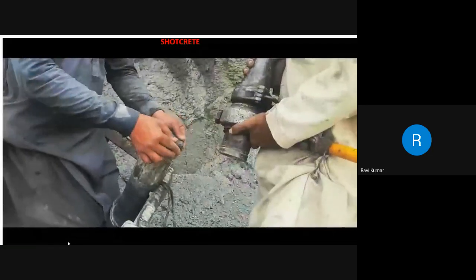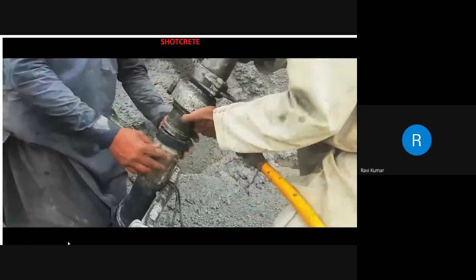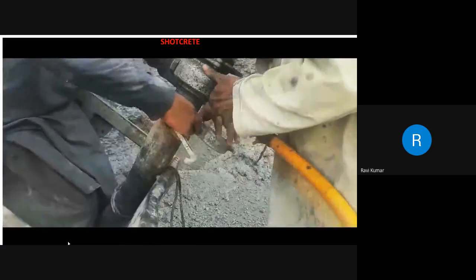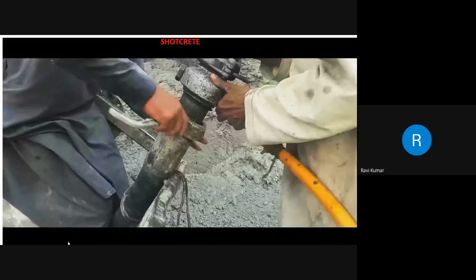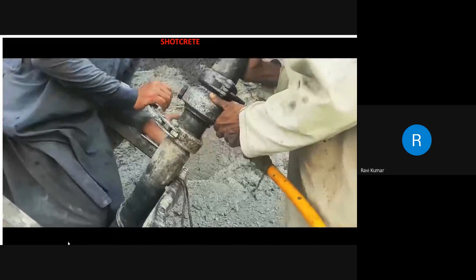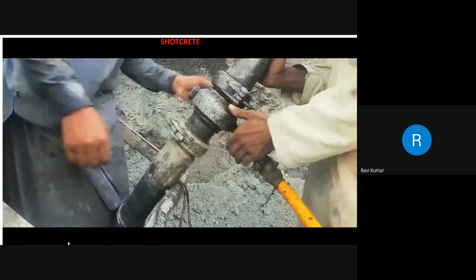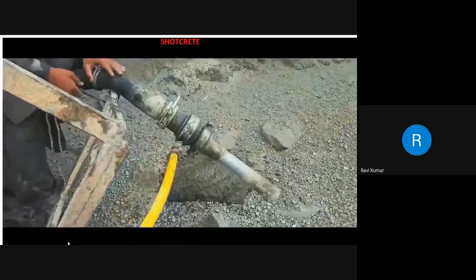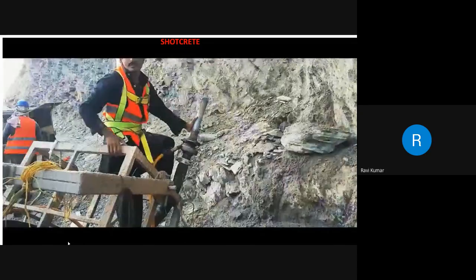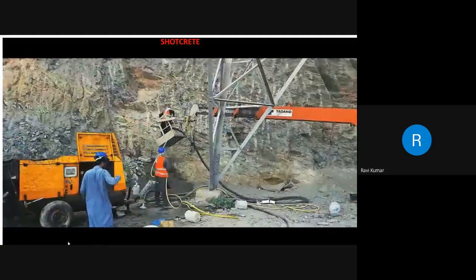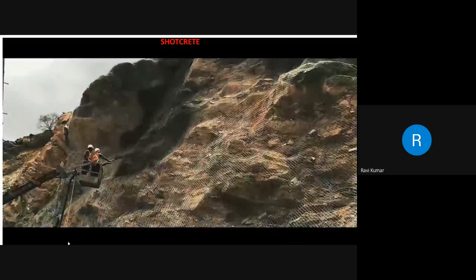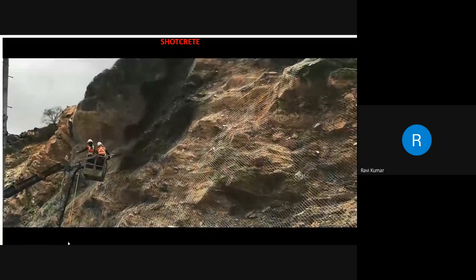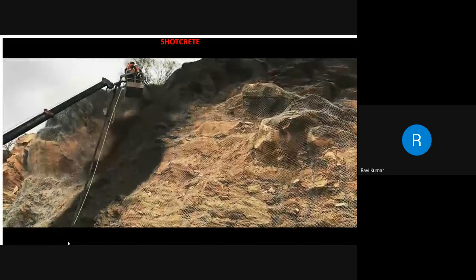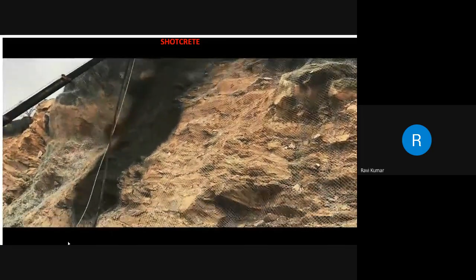Procure the concrete from the batching plant in the mix ratio of 1:1:1. Micro silica can also be added to achieve additional strength in the concrete. Pour this mix into the pump hose. Ensure to lubricate the hose pipe before starting the pump. When the pumped concrete mixture reaches the nozzle, turn on the compressor for air. This will help spray the concrete onto the surface with high velocity.